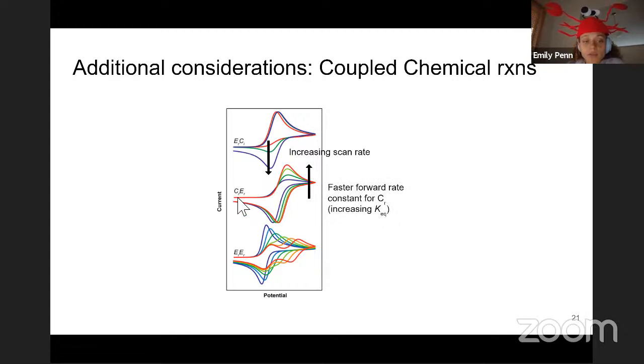Next is an example of a reversible chemical reaction followed by a reversible electrochemical reaction. Here, going from blue to red, we're increasing the forward rate constant for the chemical reaction. If the chemical reaction has a faster rate constant, then this first peak is higher. Again, you can see that the peak changes with scan rate.